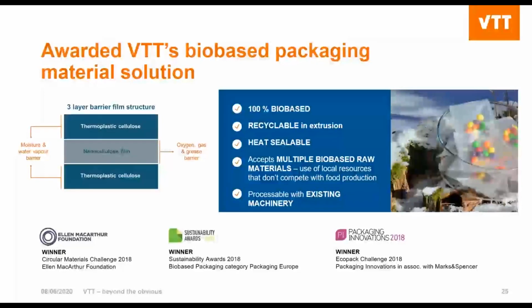It's recyclable in extrusion. We have actually tried that we can loop it back into a film 6 to 7 times. The thermoplastic cellulose also provides heat sealability since it's the outer and inner layer, and the nanocellulose film is in the middle. So the thermoplastic cellulose provides heat sealability, but also printability. And we can also process it from several different types of raw materials, as long as they are sufficient in fractions, the main limiting factor being lignin content.